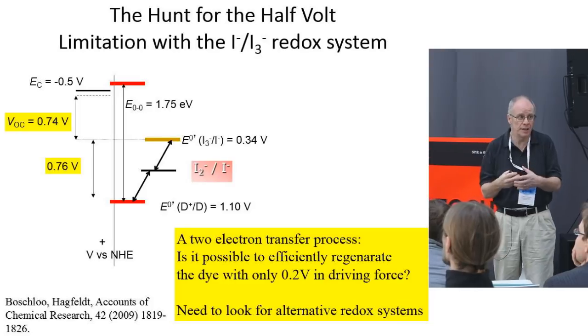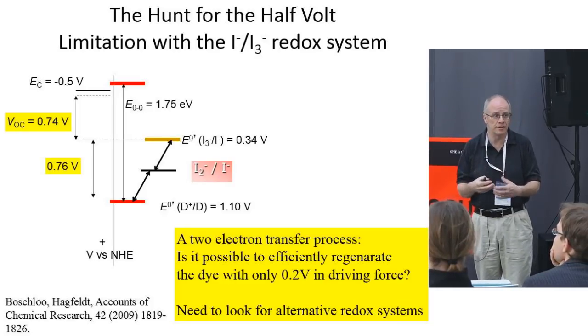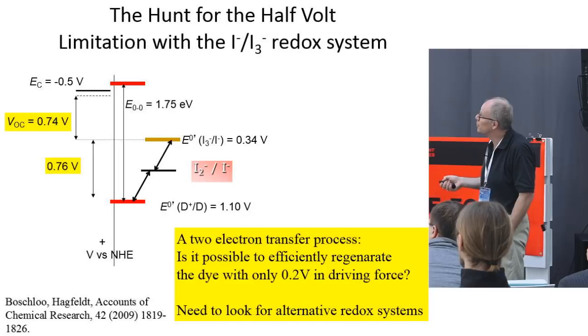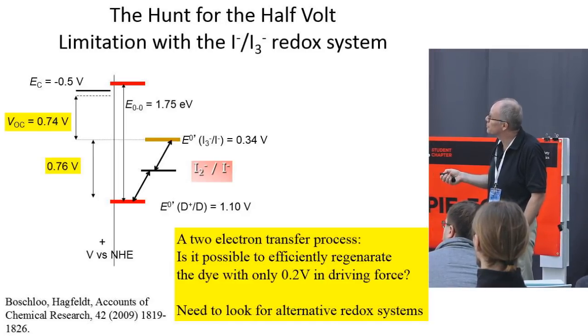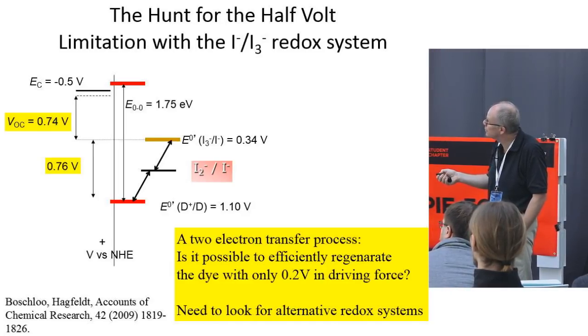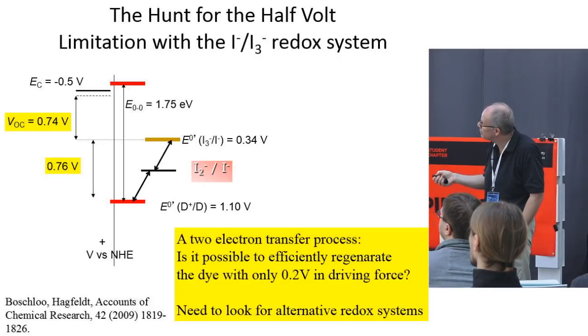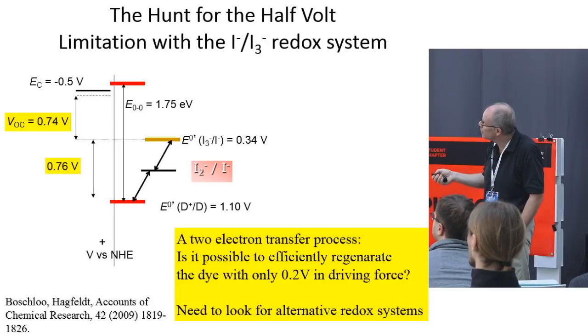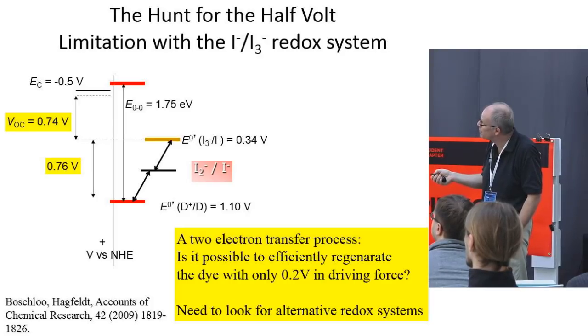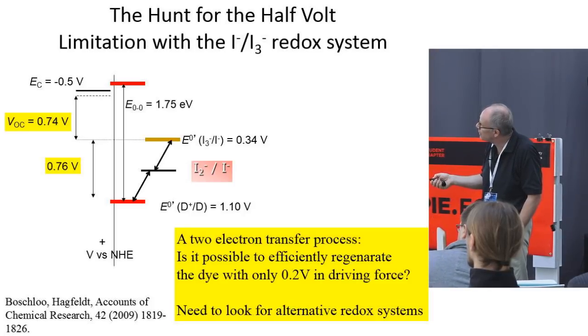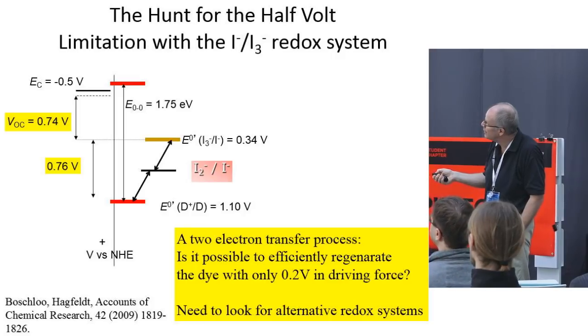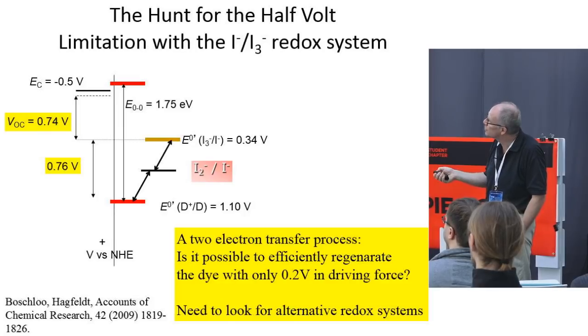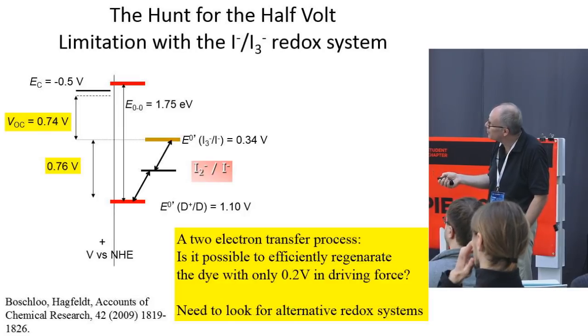And that's where we felt we can maybe get more voltage out of the system. And what to do then? Well, we should change the redox couple, of course, to something which has a more positive potential. That means that you go more in this direction, lower energy. That means that you increase the gap with the Fermi level, so higher voltage can be expected. But you also decrease the driving force to regenerate the dye. So the regeneration driving force is, of course, the difference of the redox potential and this dye here. So by going in this way, you also slow down the kinetics here.